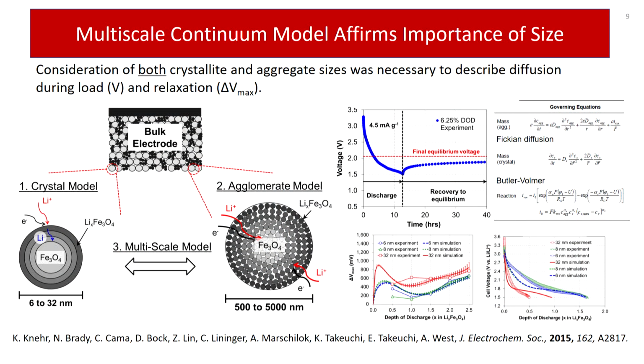Some very nice continuum modeling was done in conjunction with Alan West at Columbia University, who took on the challenge of looking at transport through the crystal using a core-shell type model and an agglomerate of these tiny crystals. And in fact, it turns out that both matter.